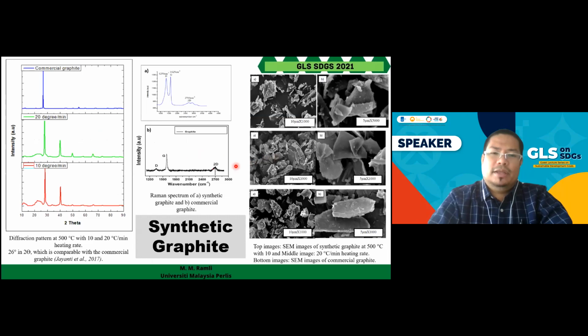So what we did was try to turn the oil palm trunk waste into synthetic graphite first. If you look at here, this is the diffraction pattern. We used XRD in order to compare with the commercial graphite. If you look at the peak here, which is around 26 to 28 degrees. Okay, so if you look at the peak here at 20 degrees per minute in terms of the heating rate, and at 10 degrees per minute in terms of the heating rate at 500 degrees C.